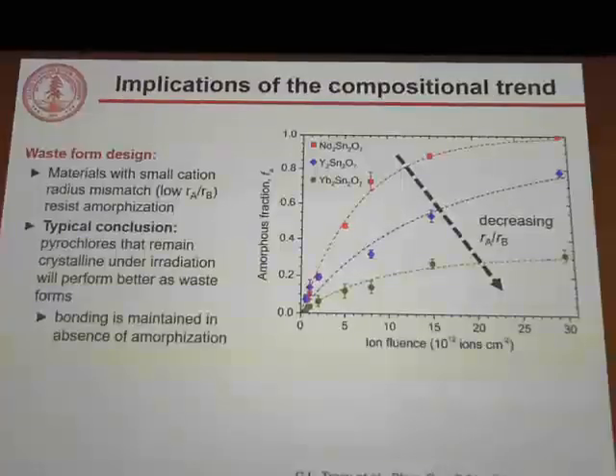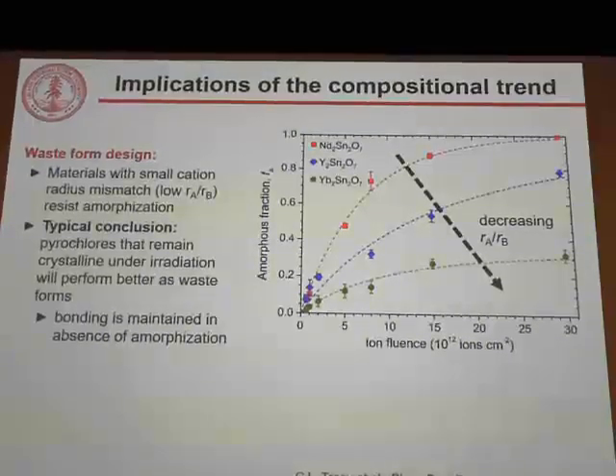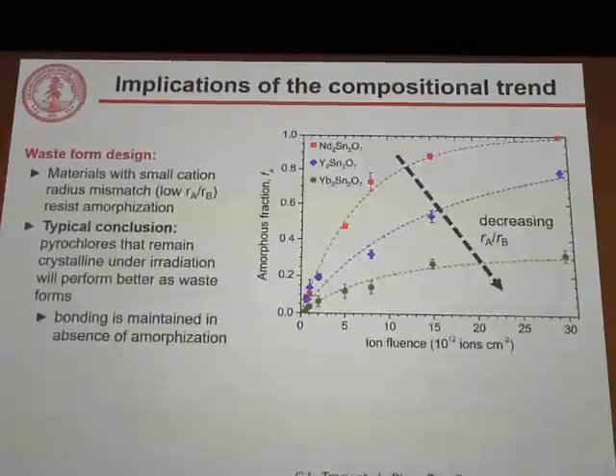Implications of this compositional trend mean that we now have a material property from which we can determine the resistance of this material to amorphization. That is the cation radius mismatch, or Ra over Rb, because we see, as in this plot here, that the fraction of material that is amorphous as a function of ion fluence decreases when you decrease this Ra/Rb ratio. So that's nice. A typical conclusion would be that we can now design better waste forms by making materials with low Ra/Rb ratios such that they maintain crystallinity when we irradiate them, because we know that in this case the bonding will be maintained in the absence of amorphization, so immobilization will still be effective.